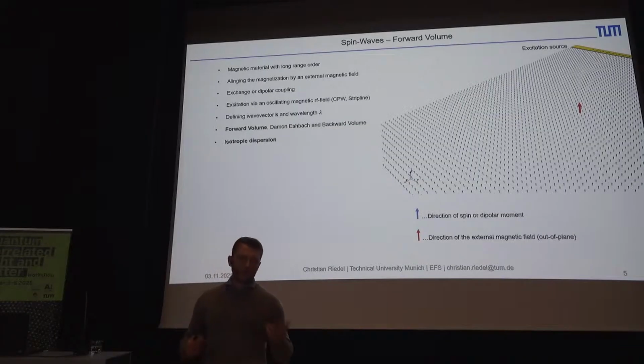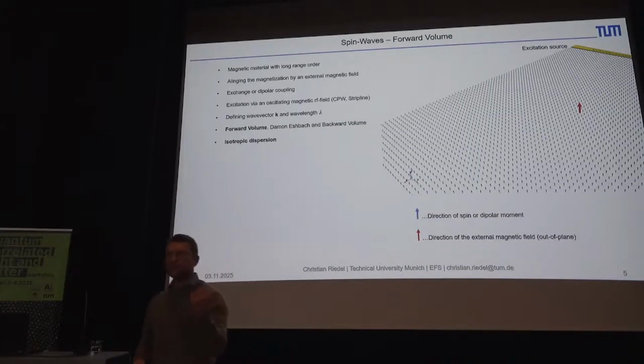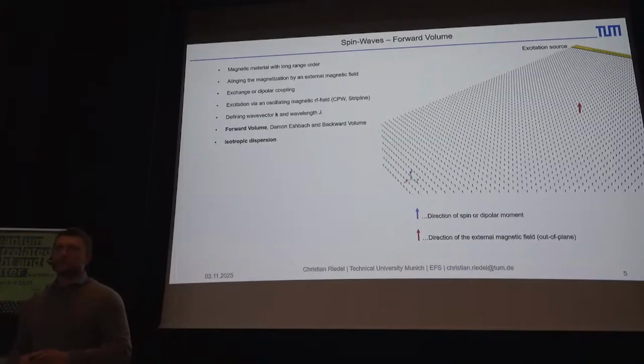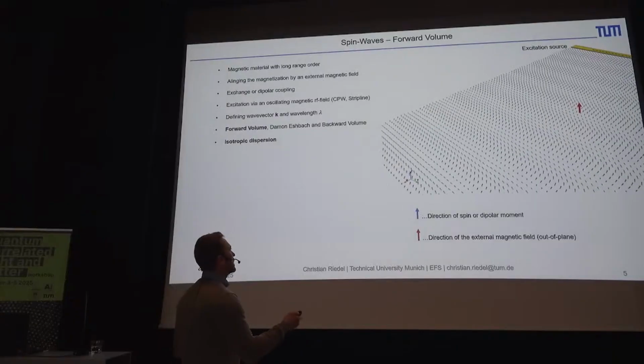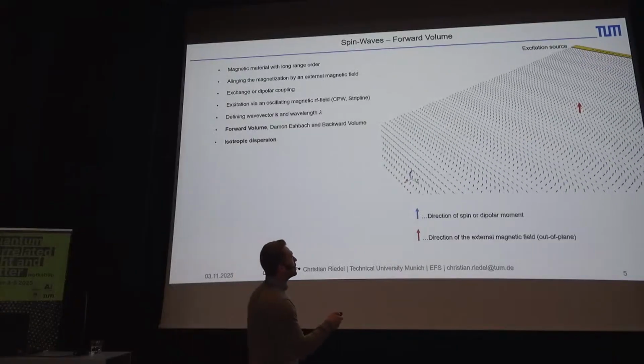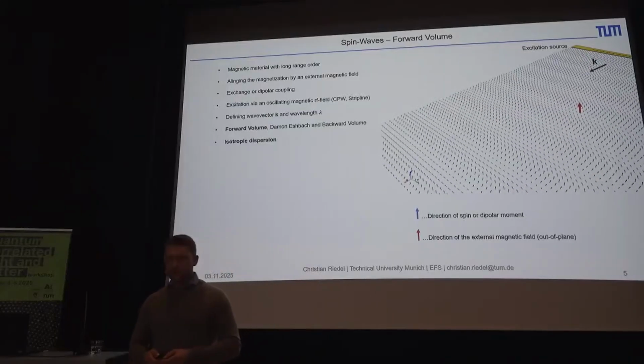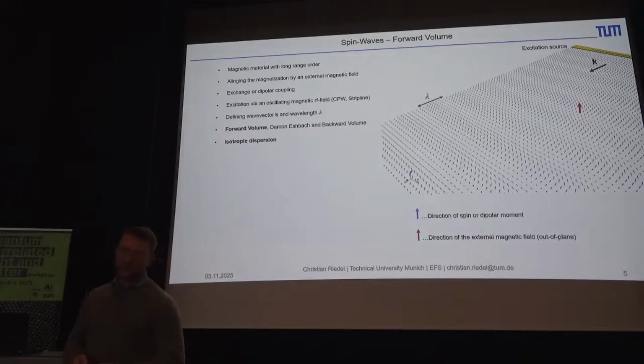While sending the radio frequency current, we create an Ørsted field around this conductor, and this Ørsted field gives you a torque on the magnetization. With this, you can excite the spins to precess, and due to the next neighbor interaction, you form a wave where we can define a k-vector and a wavelength, as for other waves.